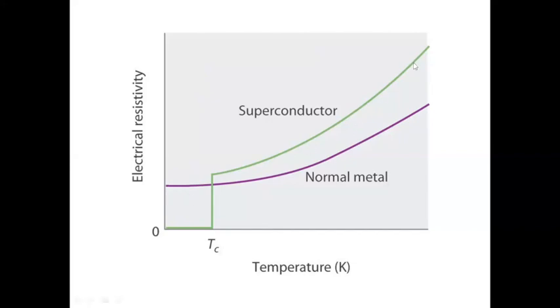Now, if you look at the superconductor transition, the first superconductor people used to call niobium, or what is it called? At the liquid helium temperature of 4.2 Kelvin. This is called the pure superconductor transition, and almost 10 to the power minus 5 ohm centimeter resistivity. But here please give your attention to the resistivity plot at a higher enough temperature, of this superconductor, to be specific, it is a BCS type.